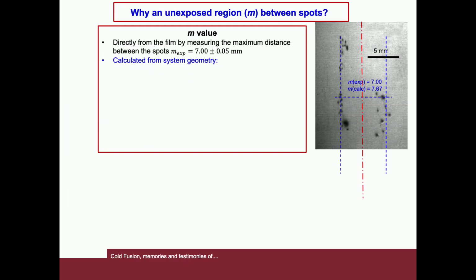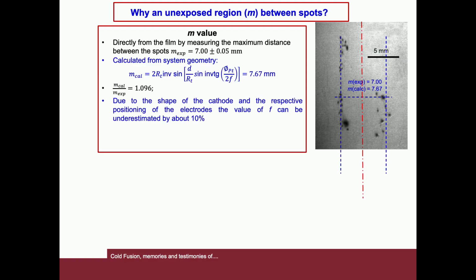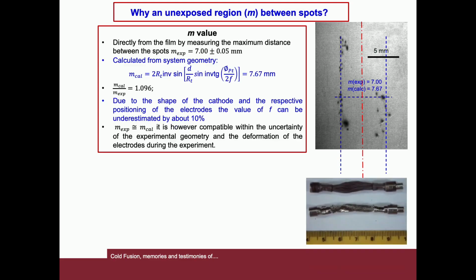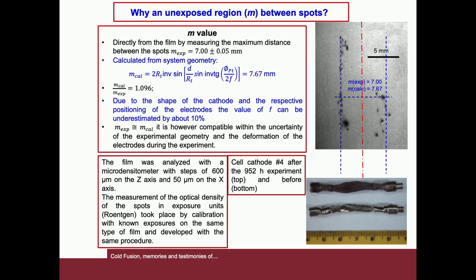Why an unexposed region between spots? As we have already seen, the measurement of the unexposed area between the spots made directly on the film is 7 mm. The calculation can be made from the geometry of the system, and the value of 7.67 mm is obtained. So the ratio between the two values differs by about 9.6%. This difference is due to the shape of the cathode and the respective positioning of the electrodes, which modifies the value of the distance f between the anode and the cathode. Furthermore, following the electrolysis, a deformation of the electrode is created.